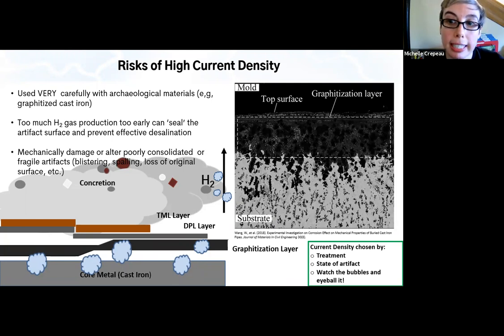We tend to want steady but not vigorous evolution of hydrogen gas. And then even that might be reduced to lower current, depending on the effect that has on the current. It's kind of a watch and see situation. So it can take a little while to establish your working settings and to get it to the place where you want it. Obviously, experience and practice reduce this time, but every artifact is different. Every artifact has its own little idiosyncrasies that you have to account for.